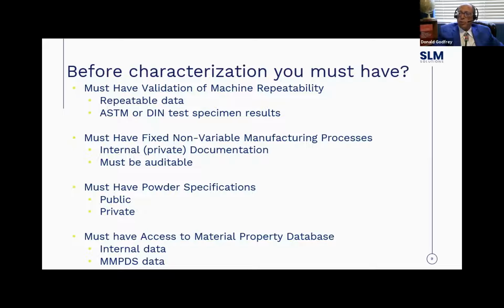Before you begin the characterization, you have to prove that your process is repeatable, meaning you're going to print 50 to 100 tensile specimens on your machine, and they're going to give you an average of X KSI, whatever that is. You're going to do that exact same build another time, and they must be repeatable. You have to be within plus or minus 3 sigma of the first round. Now, companies in the United States typically use an ASTM specimen, like an E8, and in Europe they'll use a DIN specimen. But those values should be correlatable.